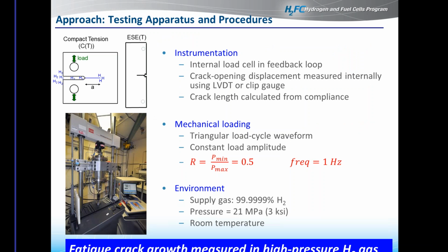So our testing capabilities here at Sandia in our hydrogen effects on materials lab are centered around this component in the bottom left, which is our custom-built pressure vessel that has been put into a commercially purchased servo-hydraulic load frame. The way it works is that the top end cap of the pressure vessel is fixed to the crosshead. The actuator essentially penetrates through the bottom of the pressure vessel and fixes to our specimen and allows us to apply a dynamic load under high pressure conditions. Now we did use two different specimen geometries, and those were just to match our material constraints. So we tested compact tension specimens as well as single edge notch tension specimens.